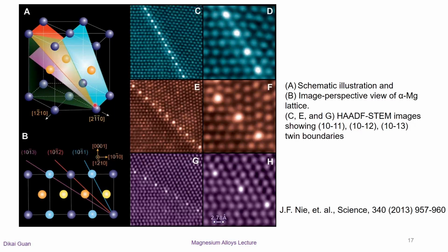These sets of high-angle annular dark-field STEM images also display three different twin boundaries, including {10-11}, {10-12}, {10-13} twinning in nanoscale. The white dots in the images are the segregated solute atoms distributed along twinning boundaries.